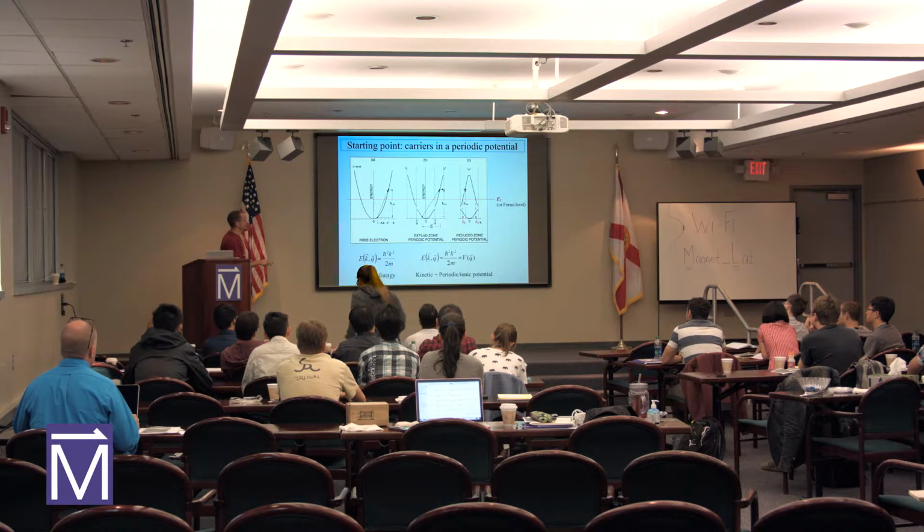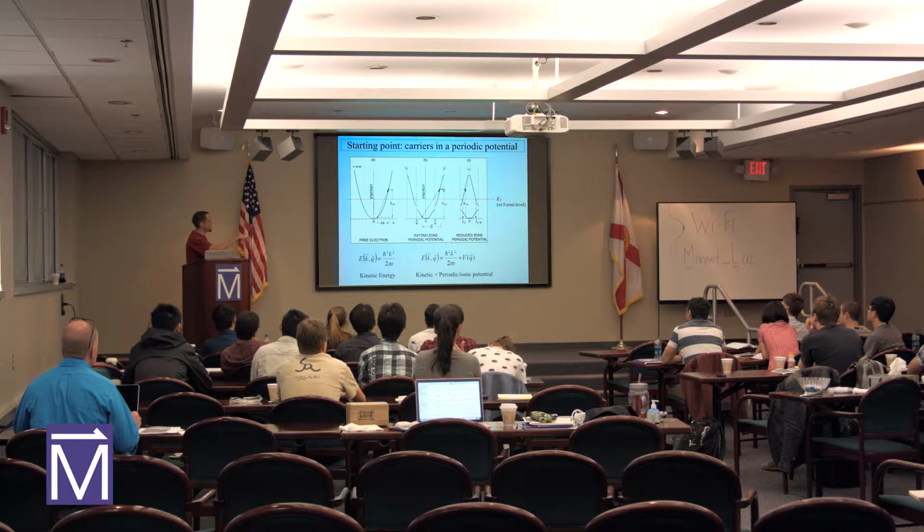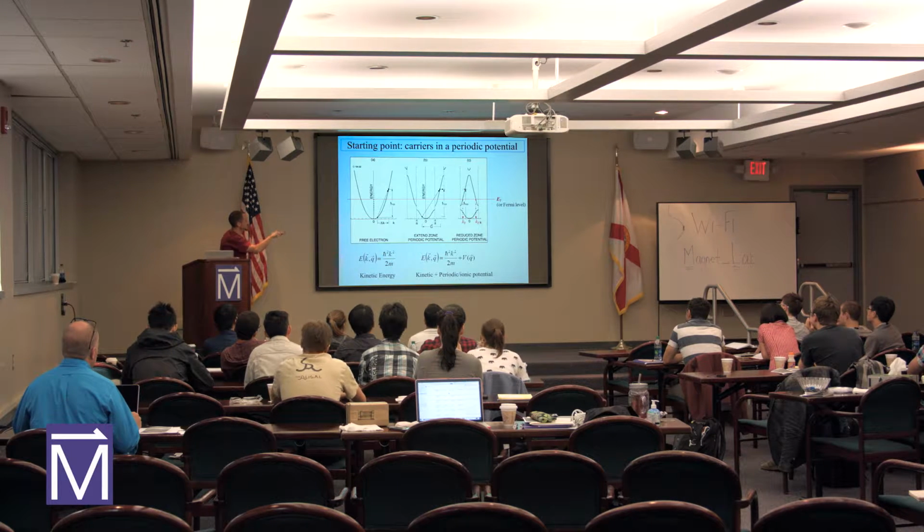If we have a lattice spacing of a in reciprocal lattice space, the boundaries will be at plus minus pi over a. And by determining the standing wave solution with these boundary conditions in place, a gap begins to open up at the edges of the boundaries. In the extended zone scheme, we get these energy bands that go off into infinity. But if we fold them back onto the same plot, we have the reduced zone scheme here. Okay, so we have bands of energy that describe where the electron energies could be.